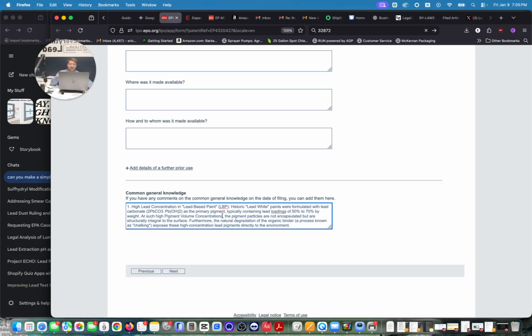So we know that historic lead-based paint contains 50 to 70% lead by weight, and it does chalk, kind of comes off in a dusty form. They actually used to say that that was advantageous because it would be easy to clean your walls because any smudges or dirt would come right off. Isn't that lovely? Lead crystal contains 24% lead oxide by weight, and that metallic lead naturally produces native oxide layers.